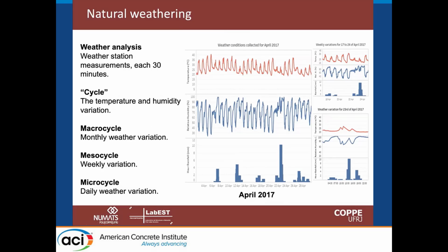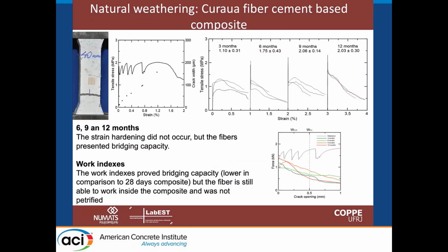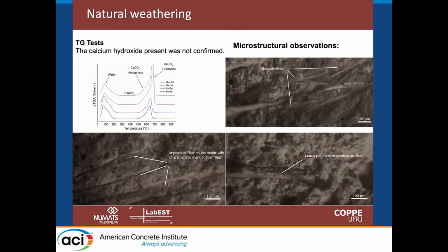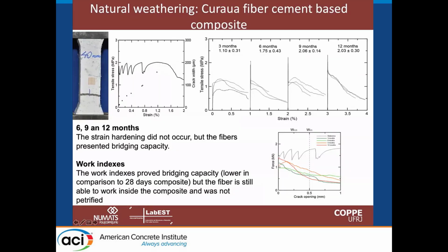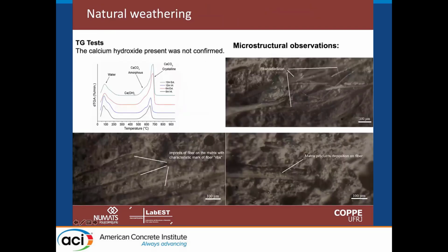And then we have several microcycles that are short term. Even in one day, we can have many of these cycles. And this can degrade the composite, even though the fiber does not mineralize. This is not the problem, but we can have a kind of fiber defibrillation, and we can lose the fiber capacity. But even so, the post-cracking behavior is quite maintained. Of course, to improve this performance and keep the original behavior, we need to use some sealant or superficial coating, in order to guarantee a longer term.